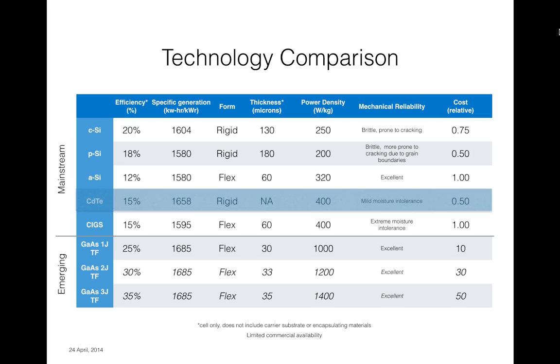And so what I did is I picked a real location, a real world solar condition, and was able to look at the specific generation. So how much energy would be collected per kilowatt rated, and that's the figure of merit. And this is the number that we compare really to determine how much energy can be collected for each of these unique materials. I'll go a little deeper into this metric later, but this is a very important metric for determining the real-world performance of the solar material, not just assessing its performance in a standard test condition in a factory somewhere, which we never see in the real world.